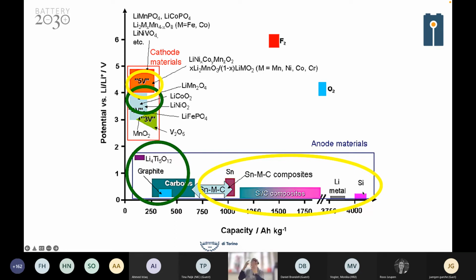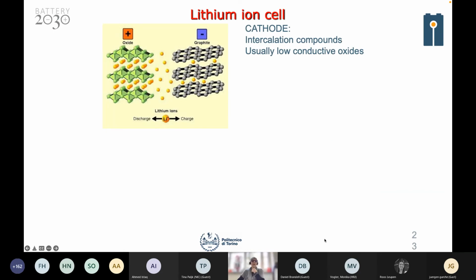as under reduction it forms alloys, it suffers from a very big volume expansion. And so we are diluting silicon, using silicon nanoparticles inside carbon matrices. So the higher the amount of silicon, the higher the capacity; the lower the amount of silicon, and consequently the higher the amount of carbon-based particles, the lower also the capacity. So the work now is to increase as much as possible the amount of silicon in the cells.